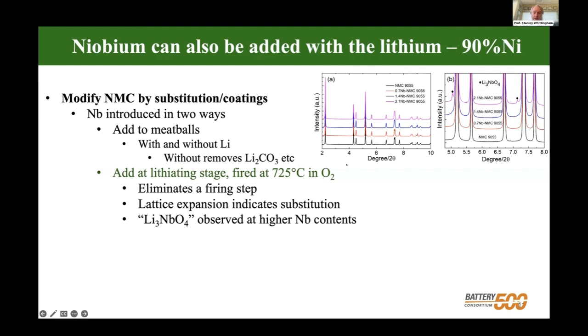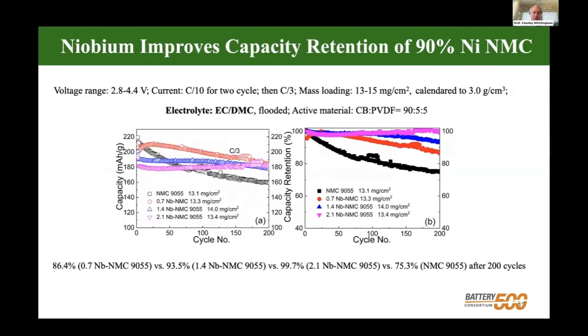What we did in the end is we actually added the niobium with the lithium at the firing stage, rather than adding the niobium compounds to the meatballs. This eliminates one whole firing step and reduces the cost of making the material. So if we look at these materials, you can see we've done 200 plus cycles on these. This is using carbonate-based electrolytes, standard cycling regime.